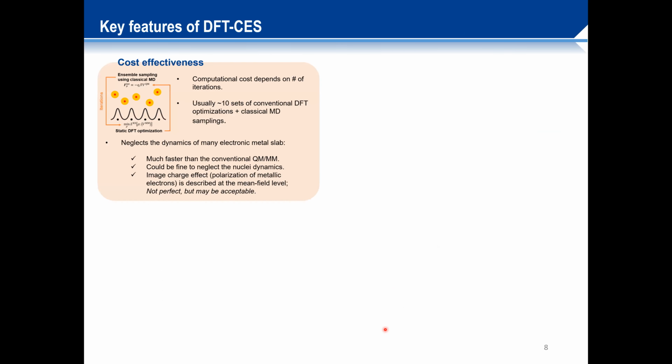Since this is more of a methods symposium, let me briefly summarize the key features of our DFT-CES. The first thing is the cost effectiveness. By neglecting the ab initio MD part, we think it is reasonable, particularly for solid-liquid systems, where the solid shows mostly vibration, just phonon dynamics. And the entire computational cost usually consists of several DFT calculations, just conventional optimization, and several MD simulations. Assuming that each of these requires around an hour, that is on the order of a day job.